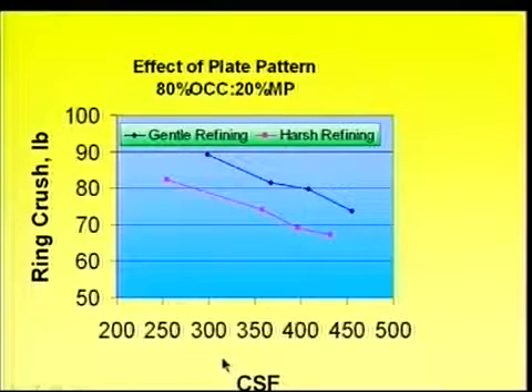Here is an example of gentle refining versus harsh refining. On the x-axis, I have Canadian standard freeness, and on the y-axis, I have ring crush, for a mixture of 80% OCC and 20% mixed pulp. When we go through somewhat harsh refining, freeness drops rapidly, but you don't develop as much strength. So we started out with the freeness of about 430-40. Then as you refine it, the freeness decreases and ring crush increases. If you go through gentle refining, you can see that we can improve the properties much more rapidly without too much drop in the freeness. In other words, for a given freeness, we can have much higher ring crush, and that is good for the paper machine productivity.